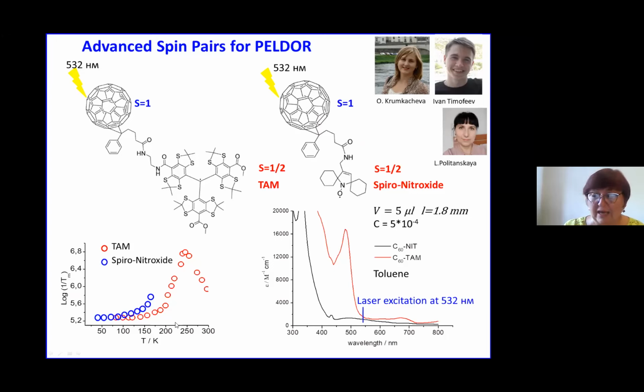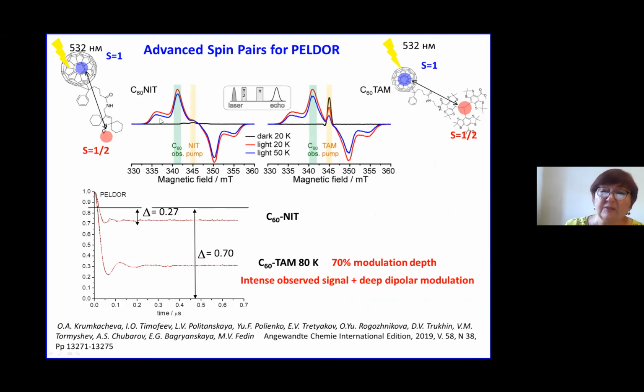The advantages, first of all, again, electron spin relaxation. So we use here a spirocyclic nitroxide, which has very long electron spin relaxation, but TAM definitely allows one to go to higher temperatures than any nitroxide. And here you see the results. You see here spin echo polarization for nitroxide and for trityl. The first point is that trityl has much narrower lines. That means it can be saturated much better, while nitroxide has quite a wide spectrum. And second, electron spin relaxation. As a result, we have much higher amplitude of modulation and much better signal to noise. So here we also have this advantage of trityls.